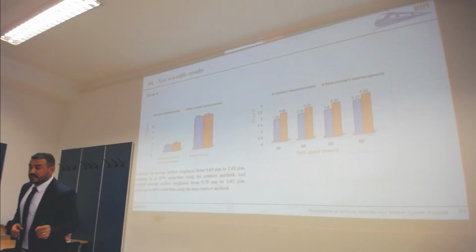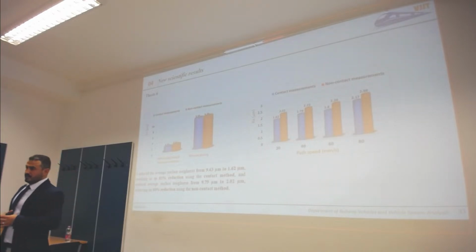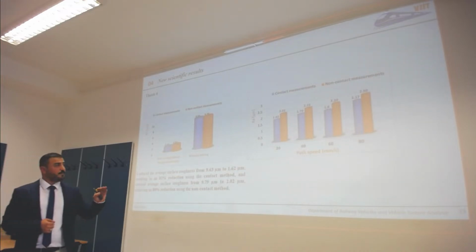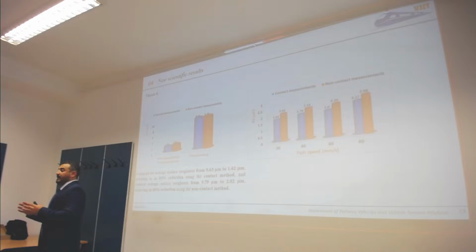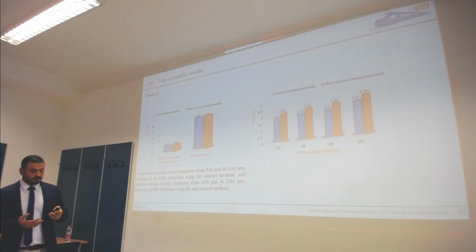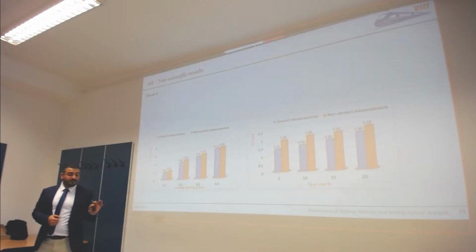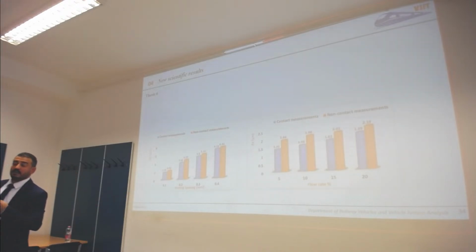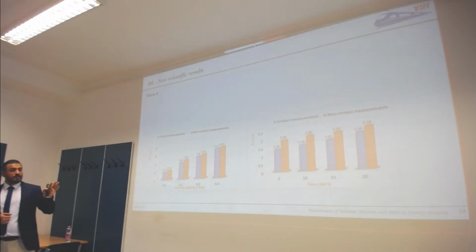Also, after that, I investigated each parameter independently to see the impact of these parameters on the overall surface roughness. For the path speed, I found that increasing path speed leads to an increase in the overall surface roughness of the parts. It was gradually increased. While for the ironing spacing, I found that by increasing the spacing between paths, the average surface roughness dramatically increased in value. For the flow rate, it's also positively correlated, but only slightly, with the value of